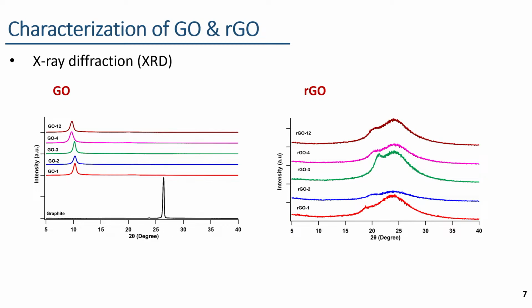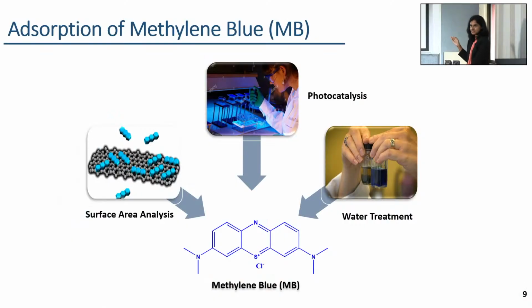Is this only for characterization, or have you identified any applications for this technique? I think I have described that. Normally the methylene blue adsorption method is used to remove methylene blue dye from effluent using graphene oxide as an adsorbent. At the same time, methylene blue is also used to measure the surface area as well as the photocatalytic activity of these GO-based materials. Those are the applications of MB adsorption with graphene oxide. But in this research, I have used methylene blue to probe the structural variations of GO and RGO. Those two differ in having methylene blue binding vertically and horizontally.